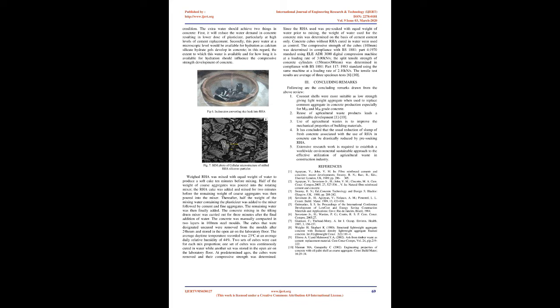The extra water should achieve two things in concrete. First, it will reduce the water demand in concrete, resulting in a lower dose of plasticizer, particularly at high levels of cement replacement. Secondly, this pore water at a microscopic level would be available for hydration as calcium silicate hydrate gels develop in concrete. In this regard, the extent to which this water is available and for how long it is available for hydration should influence the compressive strength development of concrete.